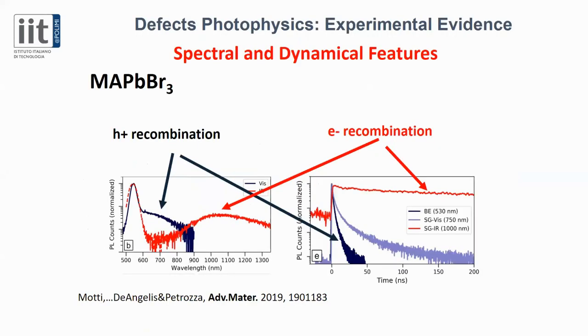What we observe from an experimental point of view. Here I'm showing an example with methylammonium lead bromide. And what we could find is actually the existence of two sub-band gap states. You can see the emission here on the left. So one in the blue, one in the red, closer to the optical edge of the semiconductor. And the one more in the near infrared has an extremely long lifetime of the order of tens of microseconds, while the one closer to the optical edge, which is responsible for trapping holes, what we experimentally prove, has on the other side a very short